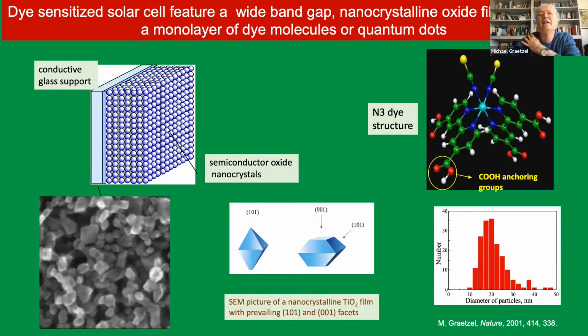But the reason why we need these nanostructured films is that if you would do this on a flat surface, you would get hardly any power conversion. The efficiencies are extremely low, below 0.1%. I mean, efficiency of solar to electric conversion. And there are various reasons for that. Light absorption is one thing. A monolayer doesn't absorb a lot of light, but there are other reasons.